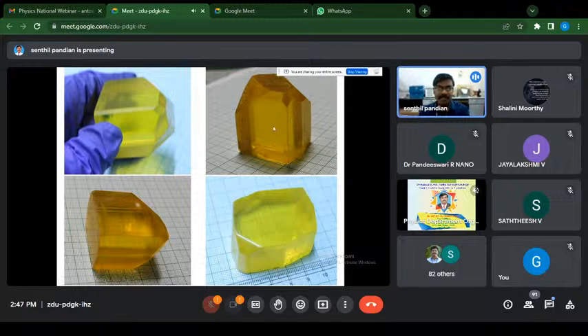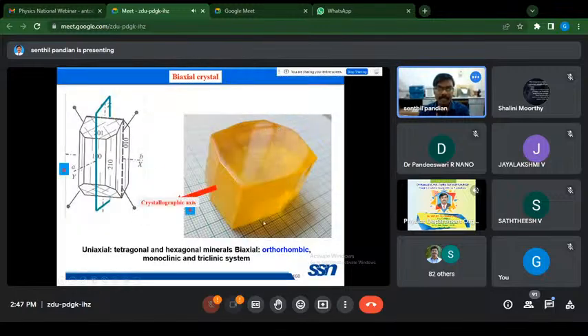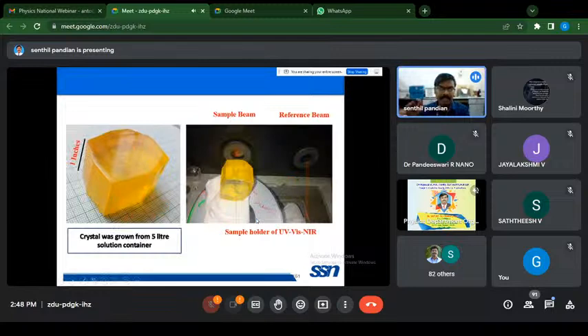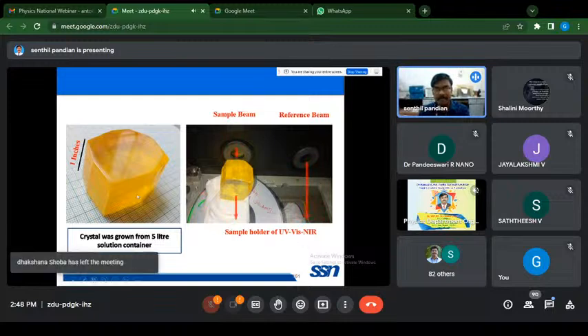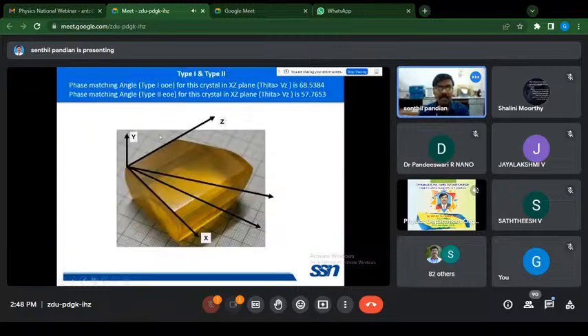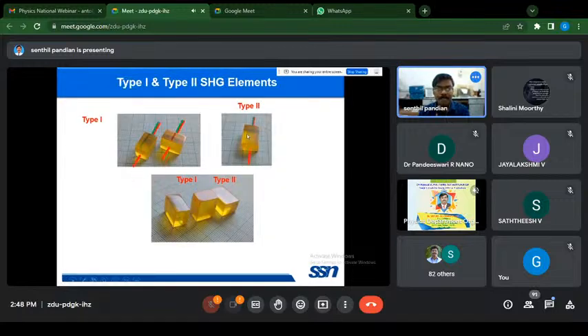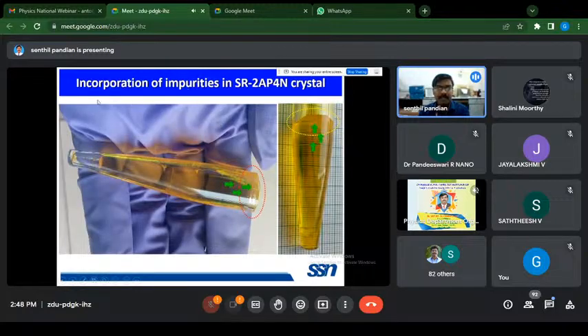From this crystal, we have successfully fabricated type 1 and type 2 SHG elements. For these type 1 and type 2 SHG elements, the SHG efficiency will be high compared to the normally grown crystal. So this is the 1-inch thick 4-substituted derivative single crystal, and we fabricated the type 1 and type 2 SHG elements. And you see some impurity incorporation in the SR method grown crystal. This is a 4-substituted derivative single crystal.